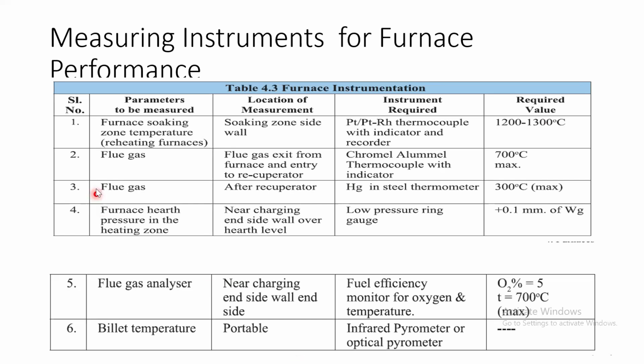So now you want to know the furnace temperature of the reheating furnace during soaking or during other operations. If you want to measure at the soaking zone, the location of measurement is the soaking zone side wall. If you want to measure it at some other location like the input side or exit side, then that side temperature has to be taken at that particular location. Now the instruments required are platinum or platinum rhodium thermocouple with indicator and recorder. It will indicate the temperature at the required location, and it will be recorded also.